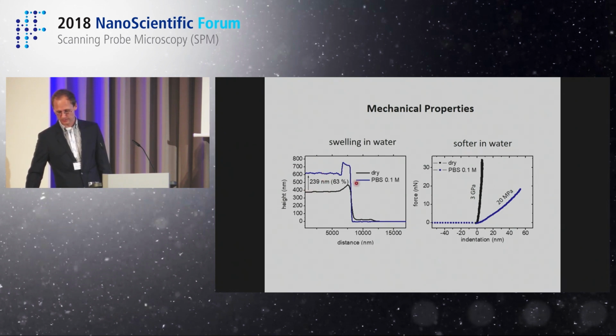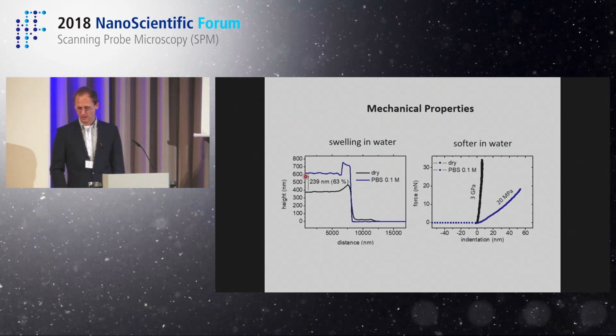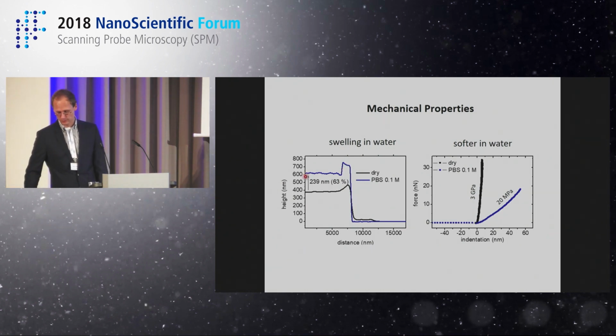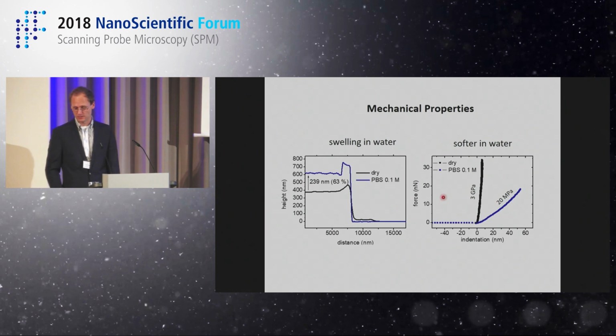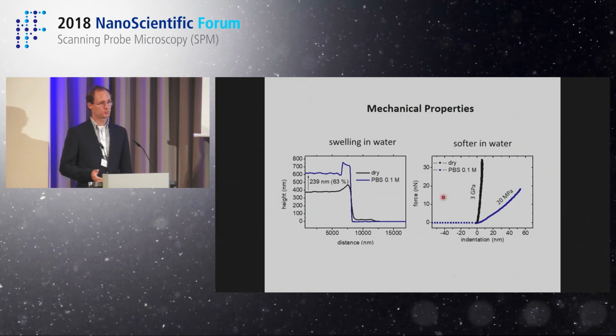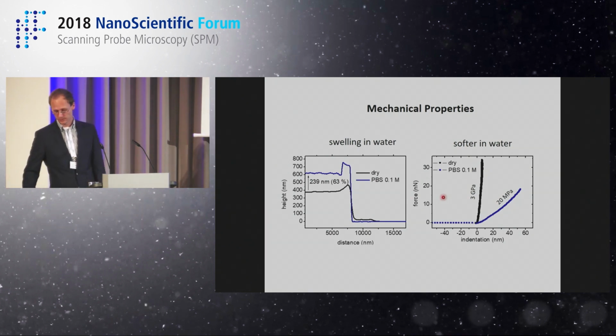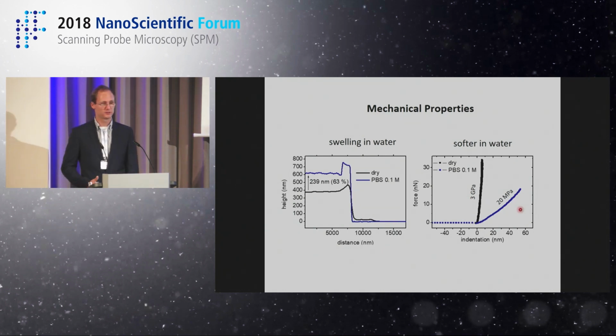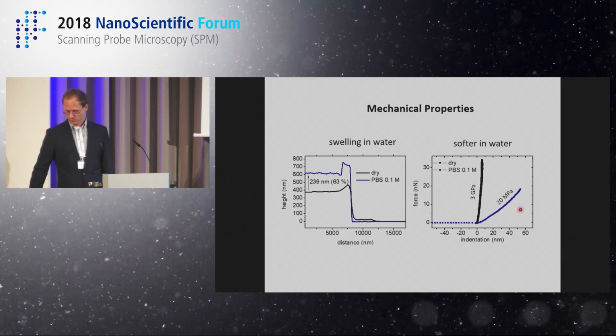So this is just as measured in air. Here there was a scratch. When you put it in water, you see there is a kind of swelling of 63%. At the same time, you also see that the mechanical properties change when you do indentation experiments. So in air, you have 3 gigapascal. If you go to liquid, you get something that is much softer and is on the order of 20 megapascals.